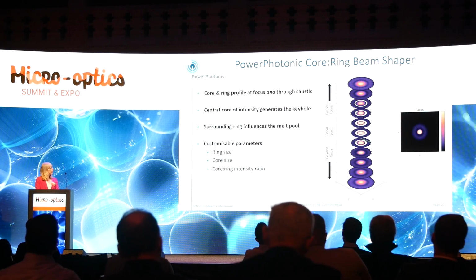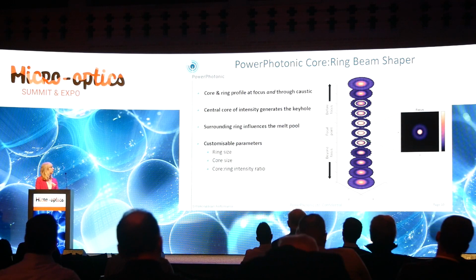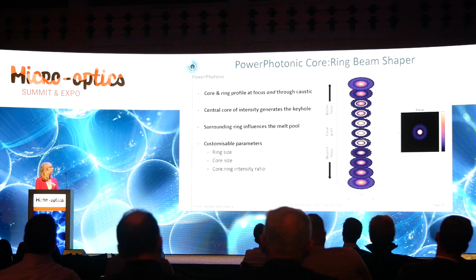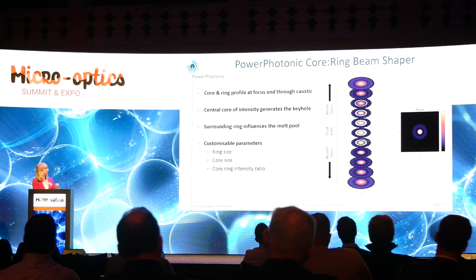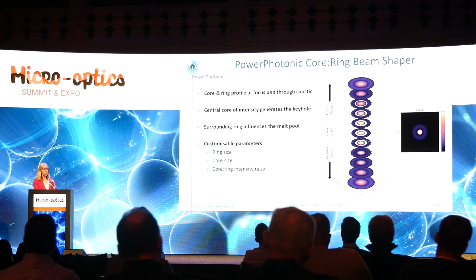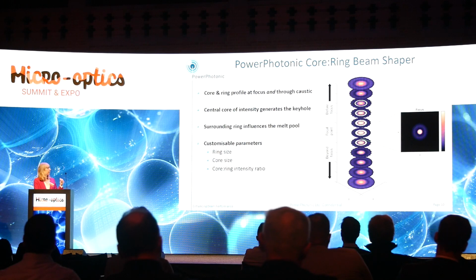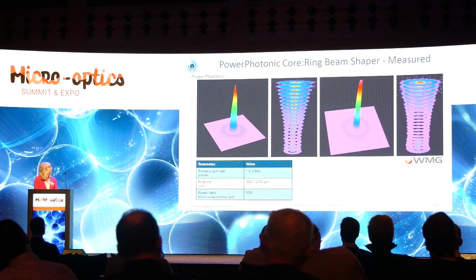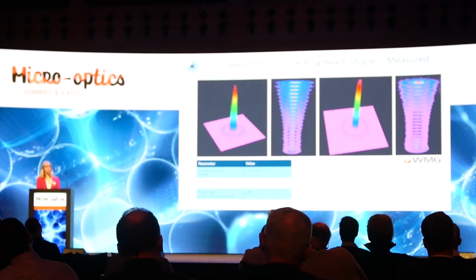This is PowerPhotonic's core and ring beam shaper. This beam shaper creates a core and ring profile at the focus, but also all the way through the caustic. The way it works for welding is the central core of intensity creates the keyhole weld, and then the surrounding ring influences the melt pool, so it helps with the spatter. It has many customizable parameters. You can change the ring size, the core size, and the core to ring intensity ratio. This is the measured data that we have from our optic.